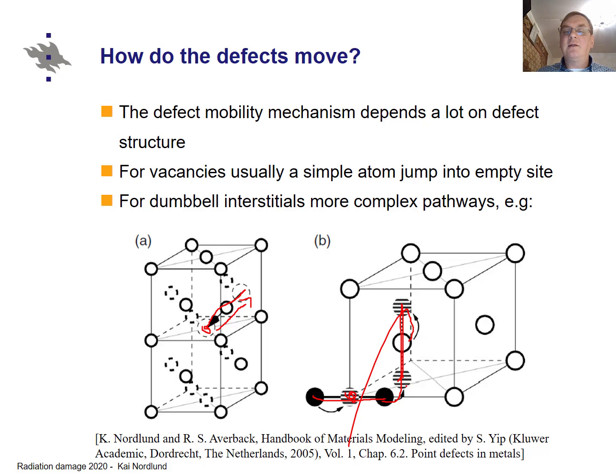And this is actually a relatively low energy barrier because the atoms are distorted initially. So this has a low migration barrier, which means that it easily happens already at very low temperatures. With the vacancy migration, you need to break the bonds of this atom to the others to get here. So the vacancy migration typically has a migration energy barrier around 1 electronvolt, which means that they start happening only at around room temperature or so. This mechanism can easily happen at a temperature of only like 30 kelvins or so.